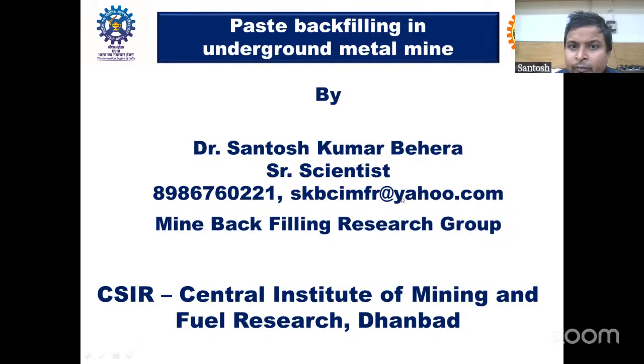So a huge volume of backfill is poured, and out of the 25% water added, 12 to 15% is consumed during cement hydration. The bleeding water, the separated water, which is the seepage water, comes out of the stope through the barricade, decantation pipes and drainage pipes. This separation of water will occur during the filling process and up to 3 or 4 days after complete filling of the stopes. Beyond 7 days there will be no seepage water. After 7 days, no water will come out of the stopes.